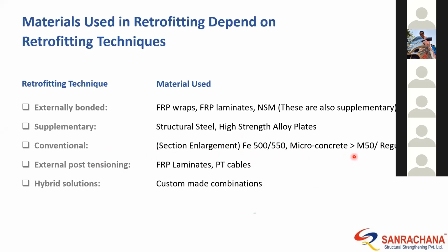Microconcrete, which is a concrete that contains lesser size aggregate. When I say aggregate, I mean the coarse aggregate. The grade of the coarse aggregate used in microconcrete can be 20 mm down or even 10 mm down. I think it comes commercially with a 10 mm down aggregate, as in the maximum size of aggregate used in the microconcrete is less than 10 mm.